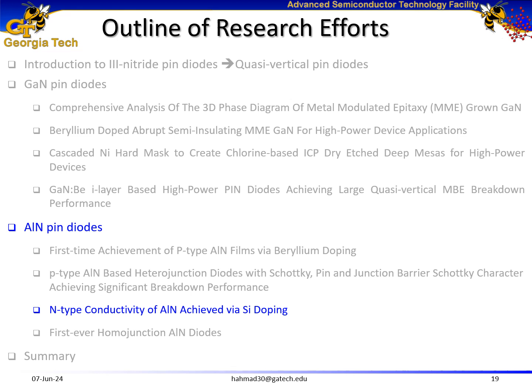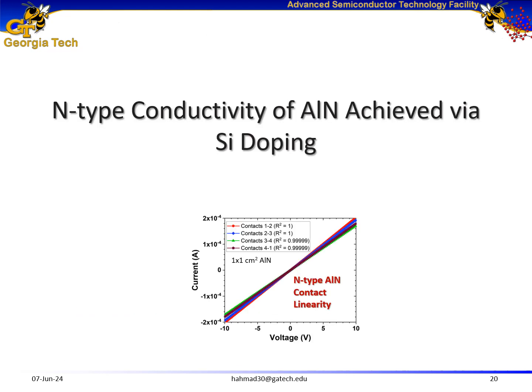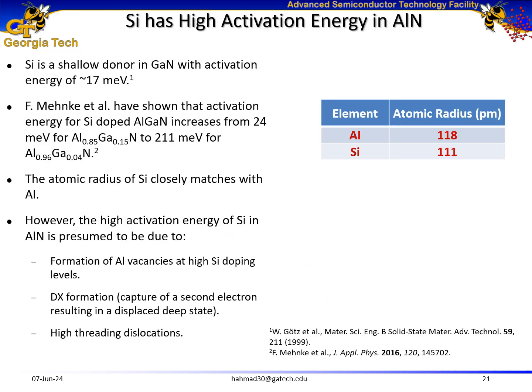Next, I wanted to pursue a research journey towards homojunction aluminum nitride, and in this regard, we introduced silicon material into one of the effusion cells in our MBE chamber. Silicon, we know, is a shallow donor in gallium nitride with activation energy of 17 milli-electron volts. However, with increase in aluminum content in aluminum gallium nitride, its activation energy increases to above 200 milli-electron volts.